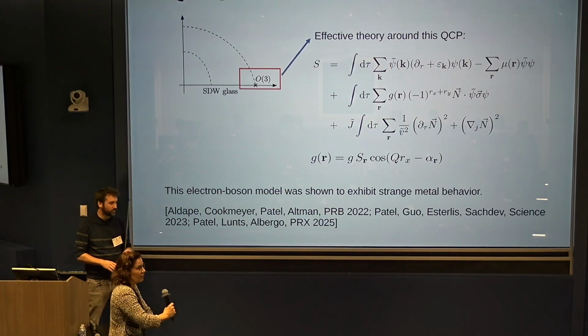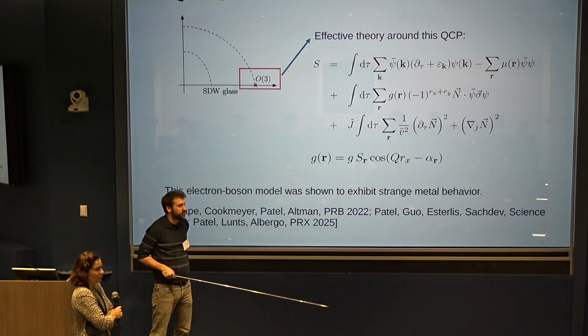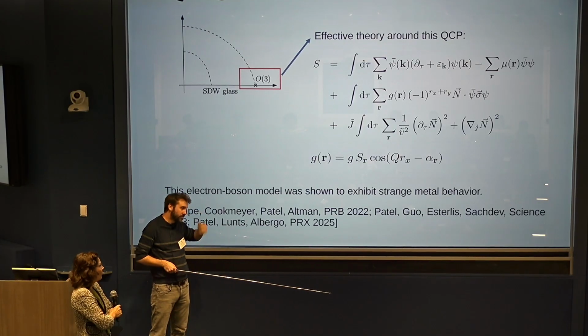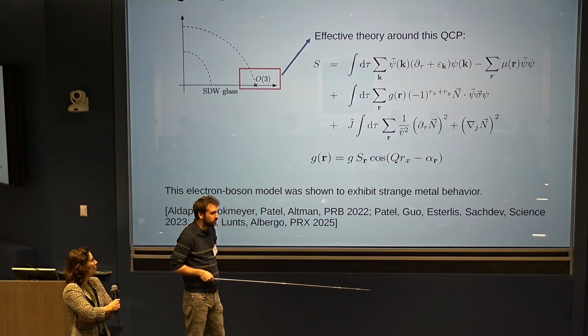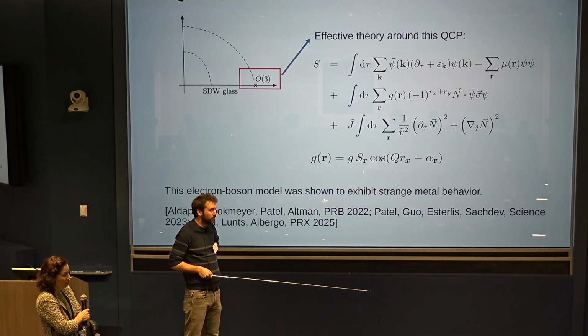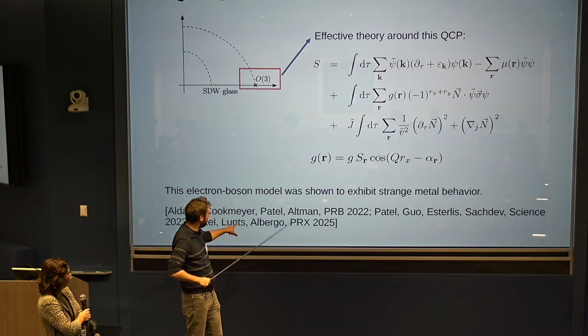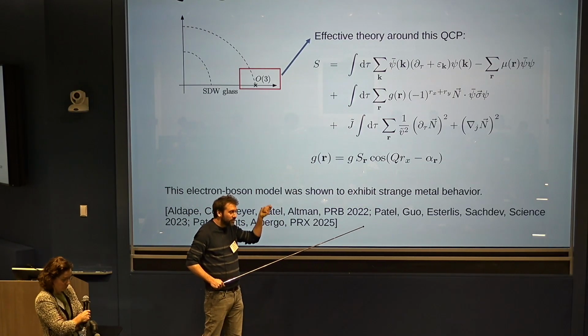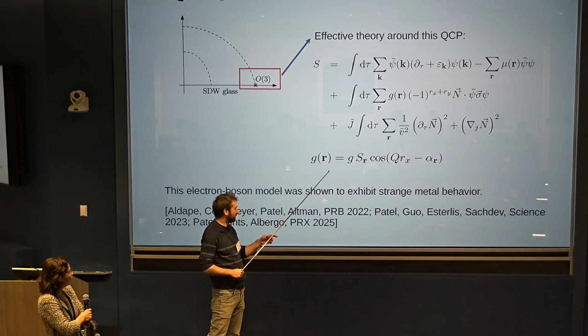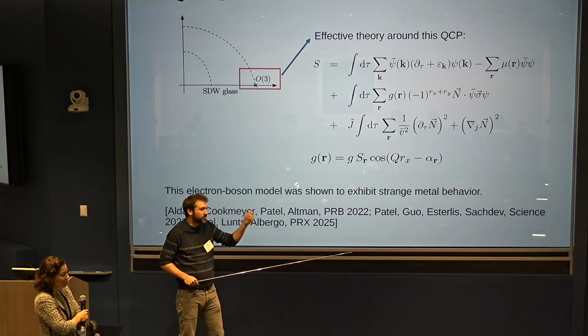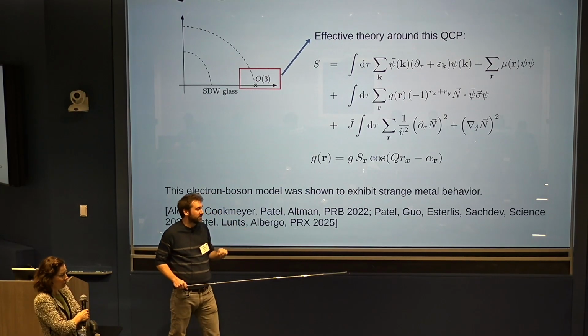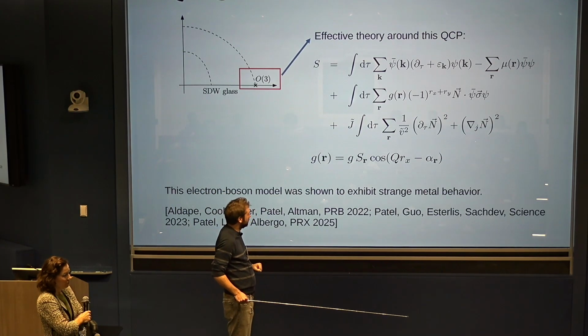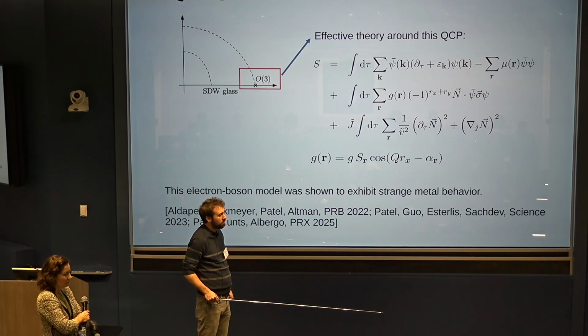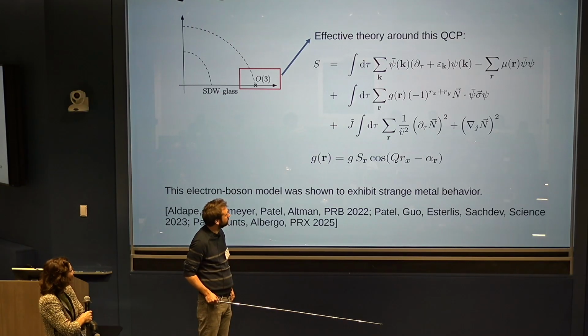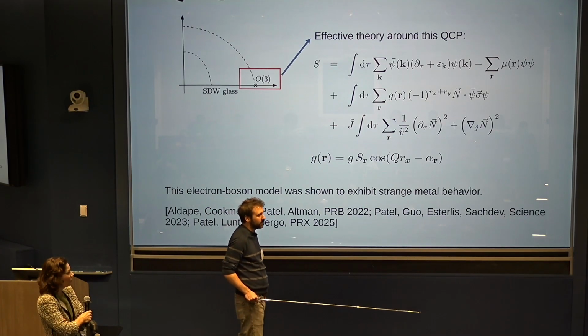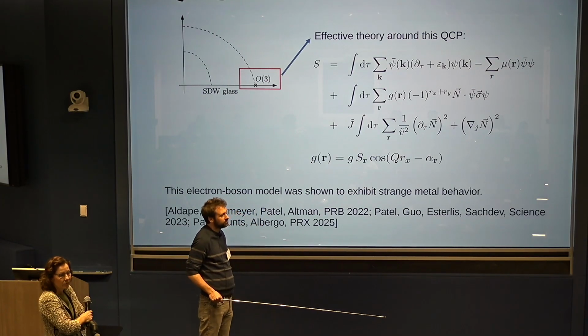Yeah, Anton? Yeah, I think that works. So if I have a finite average value of G, that's bad for strange metal, correct? Well, definitely in these original papers they claim that there will be some energy scale that will become smaller. I think they find linear T resistivity for a small fluctuating component. That would be a perturbation on top of a homogeneous part. Okay. But it would be bad for Planckian behavior. Really, my question is, how come the average value of G became 0? Because the dominant couplings are still antiferromagnetic. N is the sigma model vector for the Néel order, right? So how did you argue that G has 0 average?